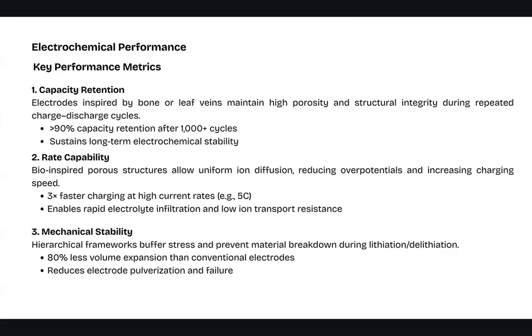Next is rate capability. These bio-inspired porous structures allow uniform ion diffusion, and this is going to reduce the overpotentials and increase charge speed. So this has shown 3 times faster charging speed at high current rates, for example, 5C. Next, it enabled rapid electrolyte infiltration and low ion transport resistance. And we have mechanical stability as the third point. Hierarchical frameworks buffer stress and prevent material breakdown during lithiation or delithiation. So there's 80% less volume expansion than conventional electrodes, and it reduces electrode pulverization and failure.